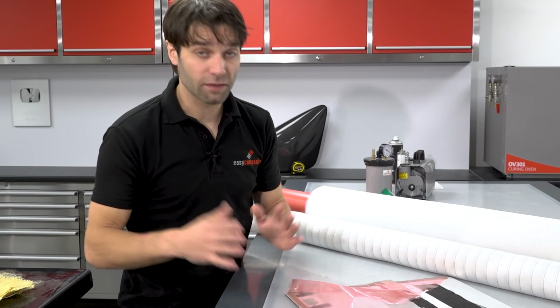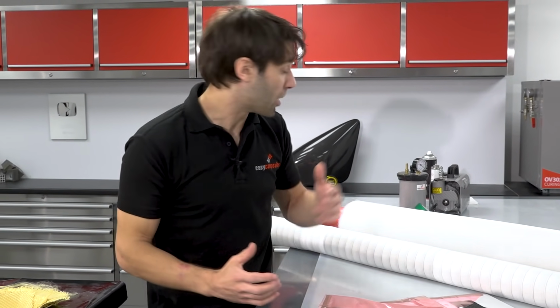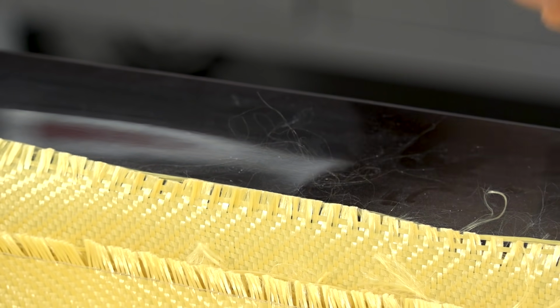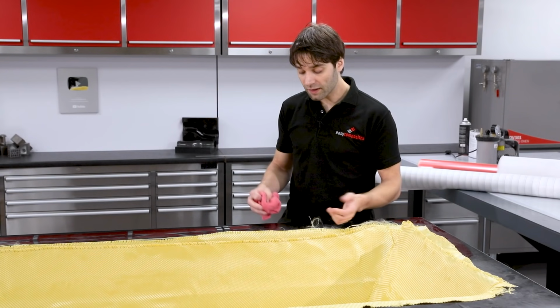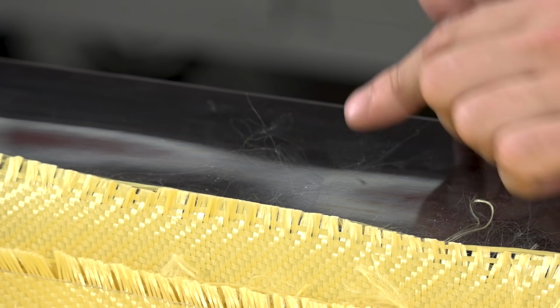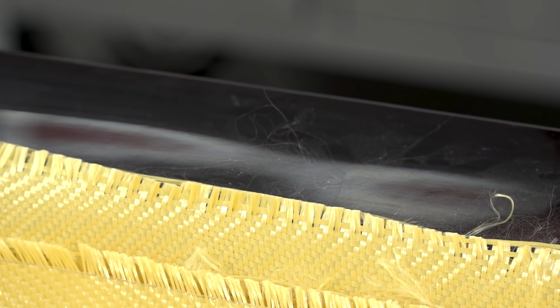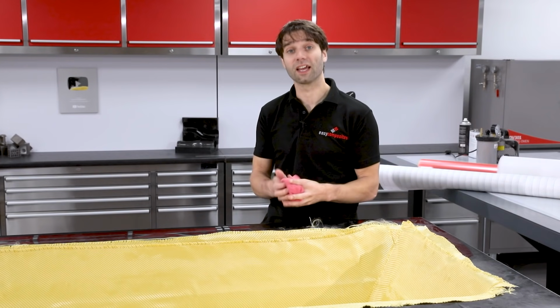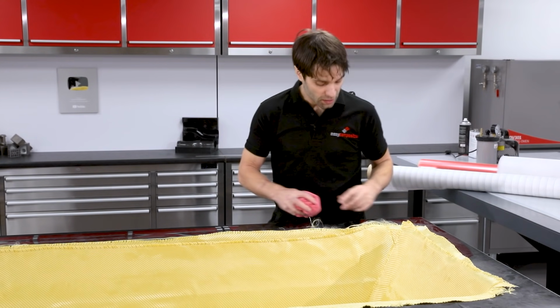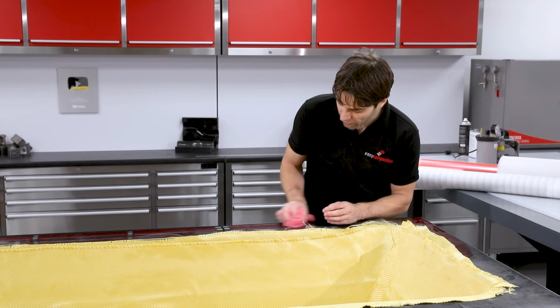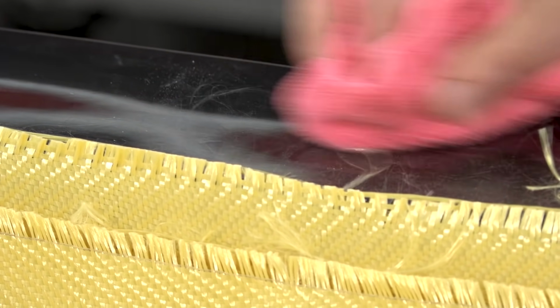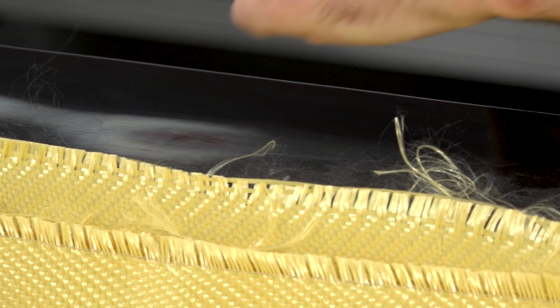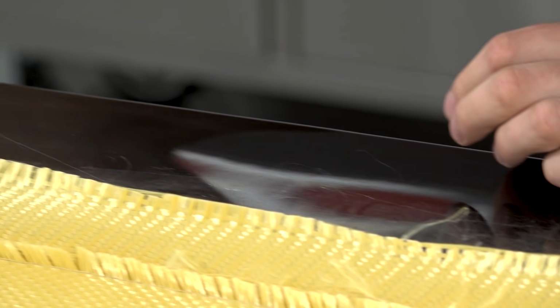So let's get started. First thing I need to do is clean the flanges of the mould, because we've got some overspray, we've got stray fibres that have come out of the Kevlar. And if, say, one of these very, very fine strands of fibre was to get underneath the sealant tape, that will cause a leak and that will cause a problem on your infusion. So we're going to just go around with a microfiber cloth, making sure that the area that we're going to tack down the gum tape onto is completely clear of any contamination.